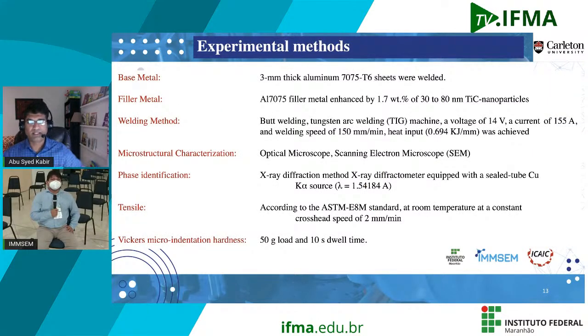So we did experiments almost the same. We had 3 millimeter thick 7075 T6 sheets, and we bought the filler metal from the same company, and that was enhanced with 1.7% titanium carbide nanoparticles. We did butt welding with tungsten inert gas welding, and we used some welding parameters, but this is the main one: heat input, which was almost 0.7 kilojoule per millimeter, which is considered to be very high heat input. Okay, I'll come back to this one.